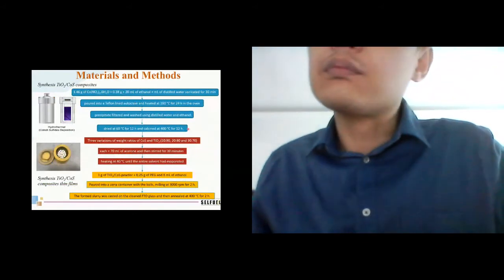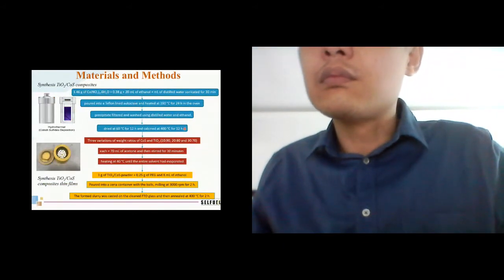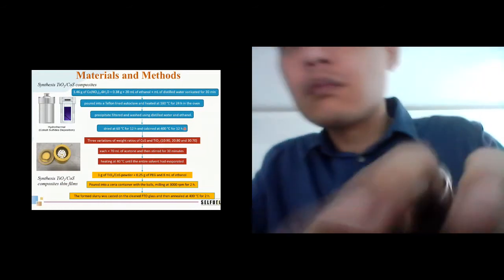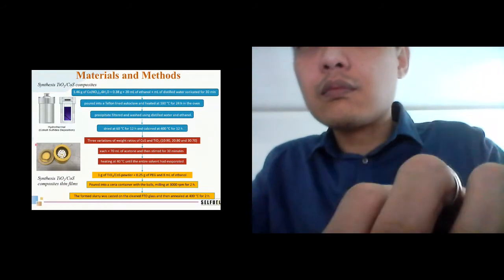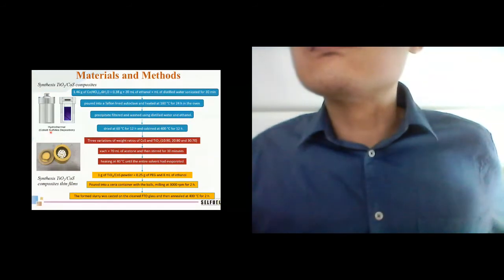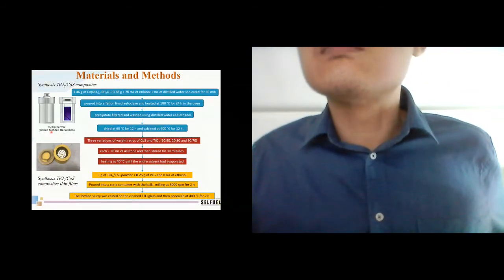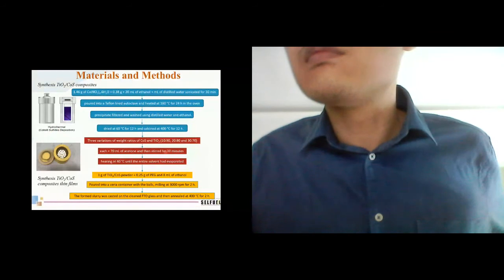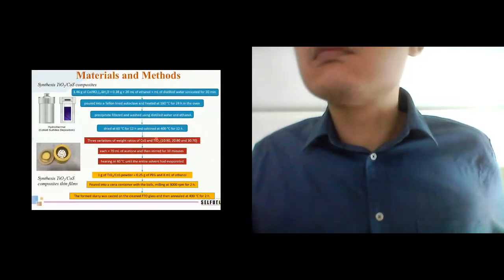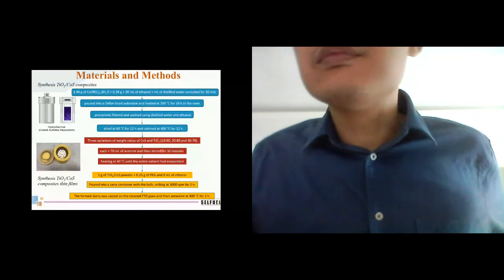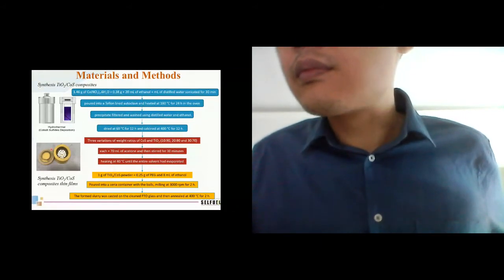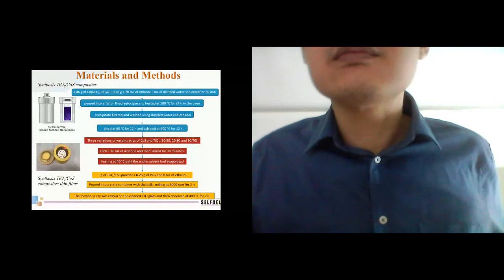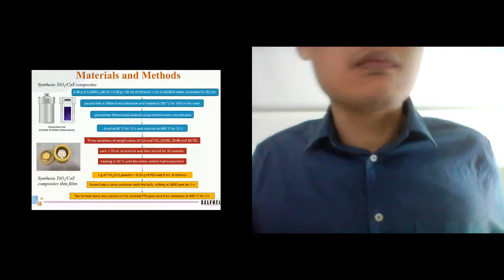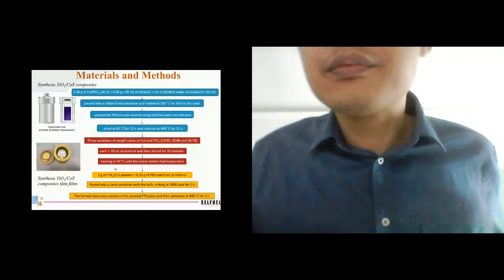The composite in this study was synthesized in a few steps. First, the synthesis of CoS by using the hydrothermal method. The CoS powder resulting from the hydrothermal method was then mixed with TiO2 Degussa to form the TiO2 CoS composite. Since the composite is in chunk form, we need to crush it to become nano size with ball milling. After that, the composite was cast on FTO glass and used for characterization.